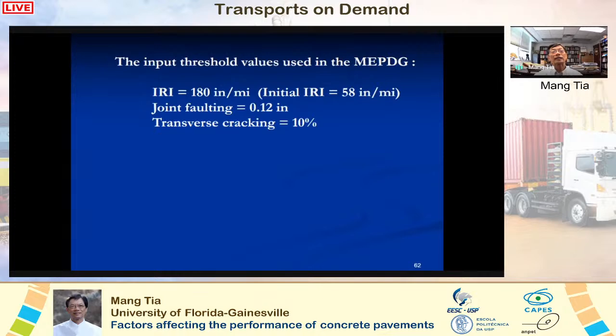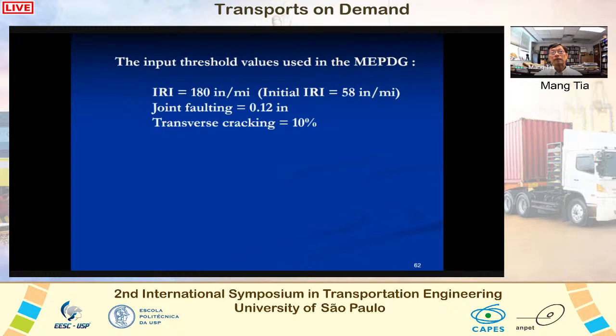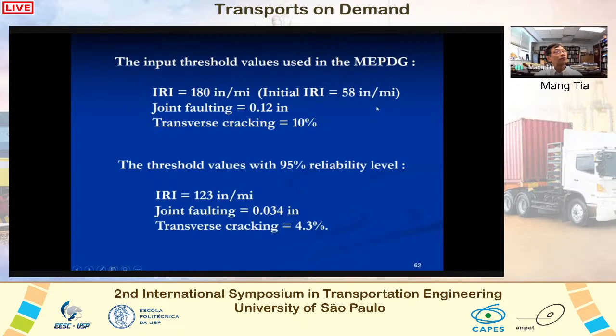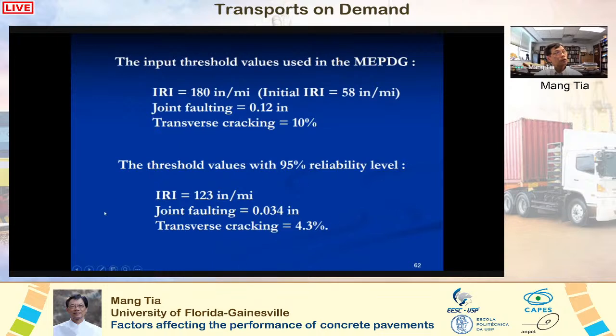The input threshold values used are given here. Okay, and we need to have an initial IRI, and the initial IRI was set to be 58 inches per mile. This is the threshold value without consideration of reliability level. So we assign a reliability of 95%. Okay. When the reliability is set to be 95%, these threshold values are now much lower. So at the end of the design life, if the predicted distress is higher than these threshold values, we would consider that the design is not adequate. Okay.